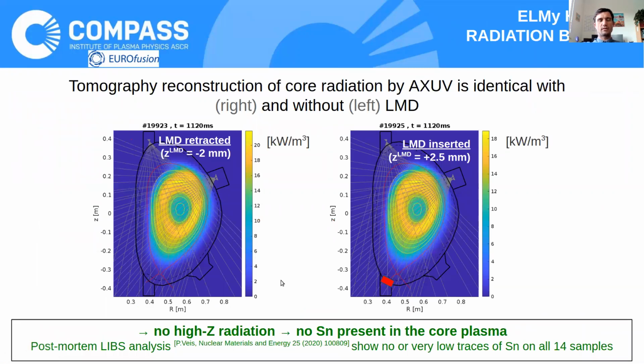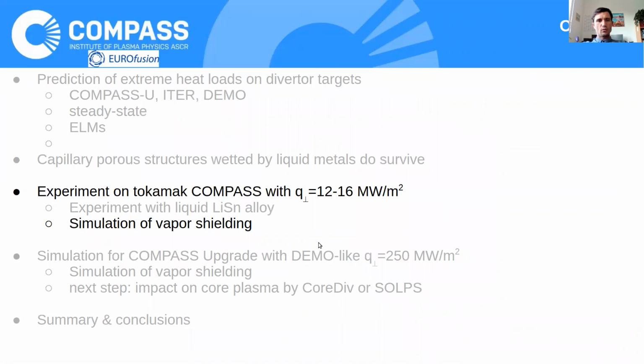We could draw a similar conclusion from the extreme ultraviolet radiation. So this is without the liquid metal target, and this is with the target included, and you see no visible difference in the pattern of radiation and also the total amount of radiation. There are no traces of tin inside the plasma which we could have observed. The postmortem LIBS analysis presented in this paper shows no or very low traces of tin on 14 samples of screws on the divertor. So now let's go to the simulation of this vapor shielding.